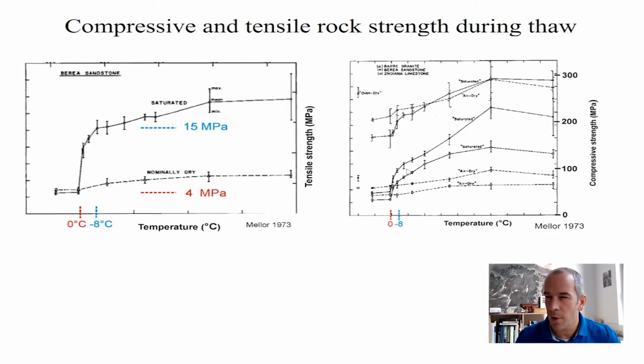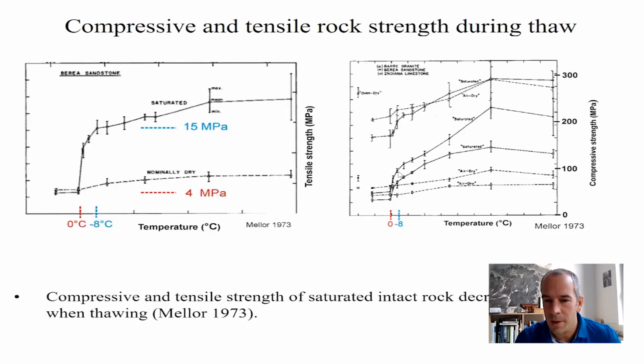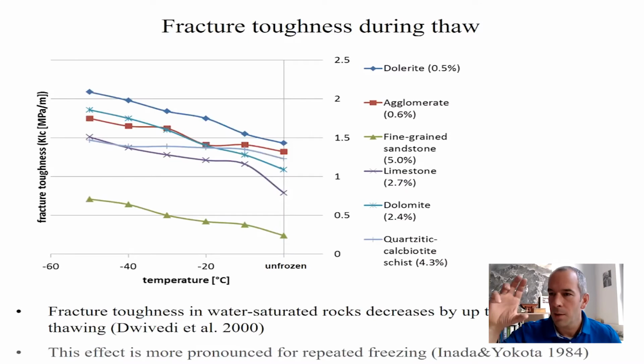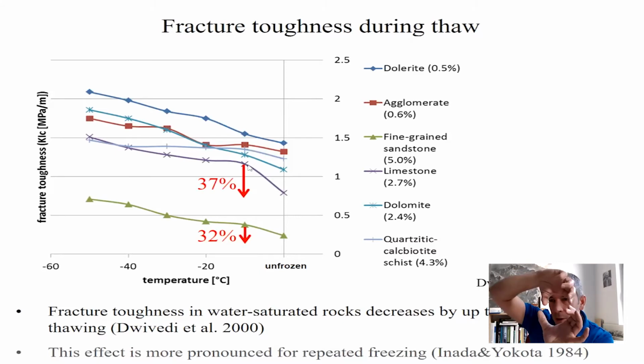And the same is true also for compressive strength. So you have a significant reduction here of the compressive strength, more in the range of 25 to 50% when it thaws. So the first thing we have to realize is that the compressive and tensile strength of rock significantly change when they start to thaw. The second mechanical factor we have to integrate into this is fracture toughness. So if I have a rock bridge like this and I try to deform it like this here, a limestone similar to that at the Zugspitze will lose 37% of its fracture toughness. Okay, and with that we can start to understand how these rock slope failures start to evolve.